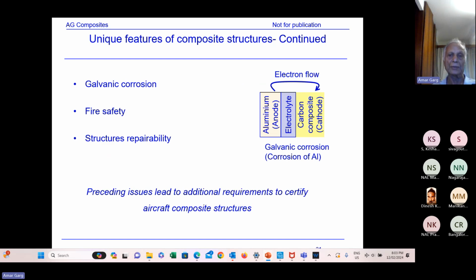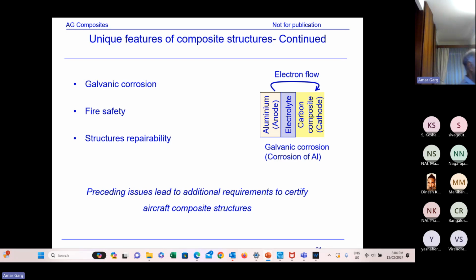Galvanic corrosion. I talked earlier about what happens with aluminum: there's some electrolyte, mainly water or moisture, between aluminum and carbon, and the electric current flows, which causes the leaching of the aluminum, that is corrosion of aluminum. So in order to protect the aluminum from corrosion, when you have aluminum sitting over a carbon skin, naturally it's likely to corrode. So to prevent that corrosion, some kind of barrier ply is introduced between carbon and aluminum. A glass fiber ply normally acts as a barrier.